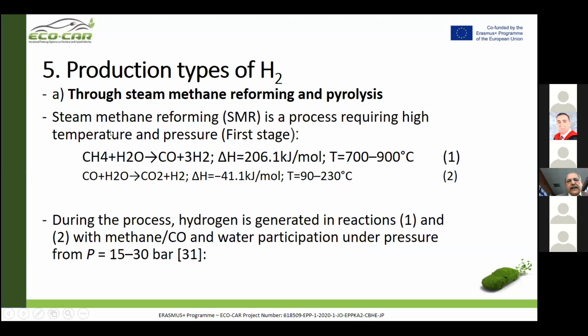pyrolysis. In this case, steam methane reforming is a process requiring high temperature and pressure. That is the first stage. In this case we need methane plus water. Then as a result, we have CO, carbon monoxide, plus hydrogen. In this case, we have about 206 kilojoule per mole. And for that, we need high temperature. Therefore, the process requires high temperature, about 700 to 900 degrees centigrade.